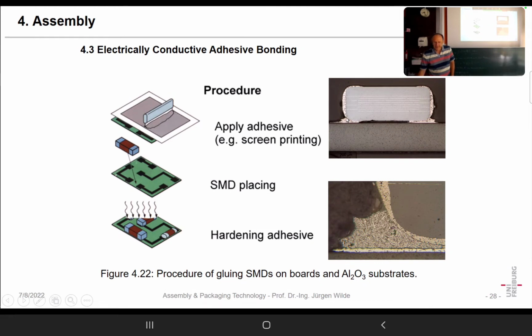What we want to achieve is, for instance, a capacitor or some other device that is glued onto a thick film substrate. Here we see that's aluminum oxide. Here, these white lines are silver palladium. And in between here, we see the adhesive. The adhesive consists of epoxy and roughly 88% of silver flakes. So it's silver flakes or powder, and these are mixed into the epoxy.